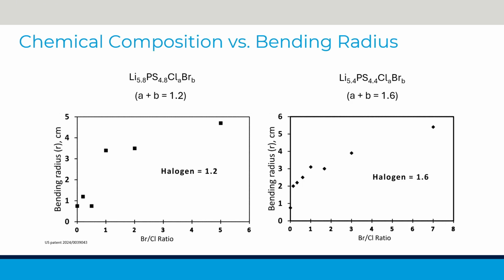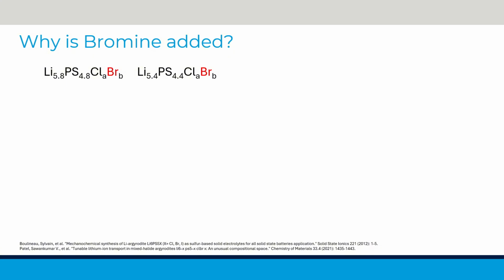Argyrodite-type sulfide can have different doping amounts to fine-tune its properties. These two plots show the relationship between the bromine-chlorine ratio and the bending radius of solid electrolyte membranes. Both figures show that a lower molar ratio of bromine-chlorine gives better flexibility. When there's no bromine doping, it exhibits the best flexibility. But why is bromine added?